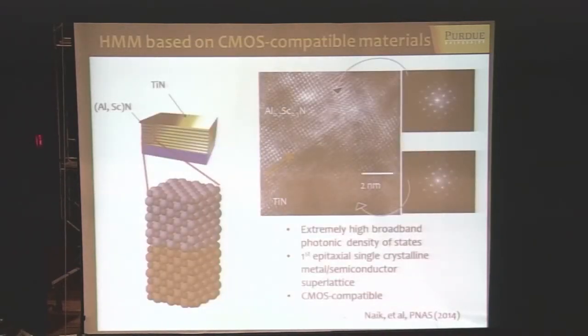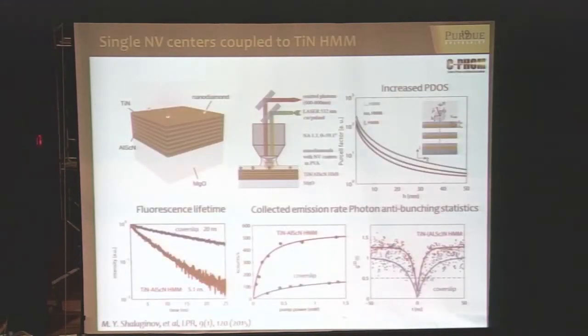What we did was make hyperbolic metamaterials out of titanium nitride. From the perspective of metamaterial scientists, this is a beautiful structure because they tried for decades to combine metals with semiconductors and grow a superlattice. It's a huge challenge because they typically have very different structural lattices, and we succeeded in doing so. We have single crystal titanium nitride combined with a dielectric based on aluminum nitride, but we had to add a little scandium to match the lattices. As a result, we obtained one big superlattice consisting of 20 layers of plasmonic material, titanium nitride, 5 nanometers thick, and 20 dielectric layers consisting of aluminum scandium nitride. This is just an overview of what we obtained.